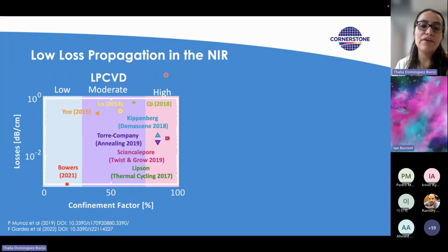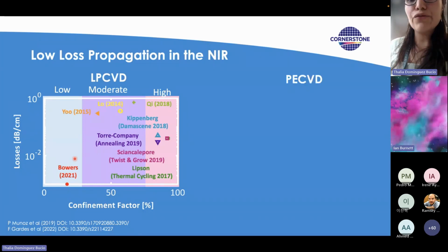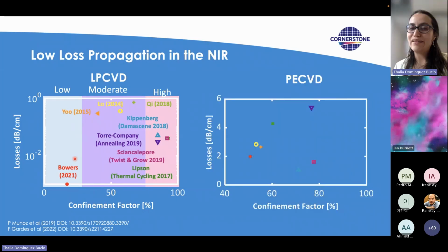You have waveguides that can have losses below 0.05 dB per centimeter using processes like the Damascene process and multi-step annealing. You can do a technique that is called twist and growing, which basically you grow half of the thickness of your layer and then you twist it again, and also do some sort of cycling. And that's how you can achieve these ultra low losses in high confinement waveguides and in low confinement waveguides using LPCVD silicon nitride.